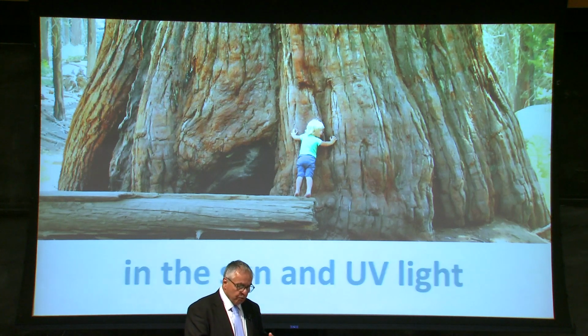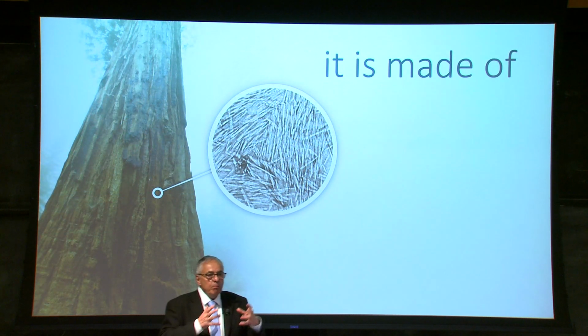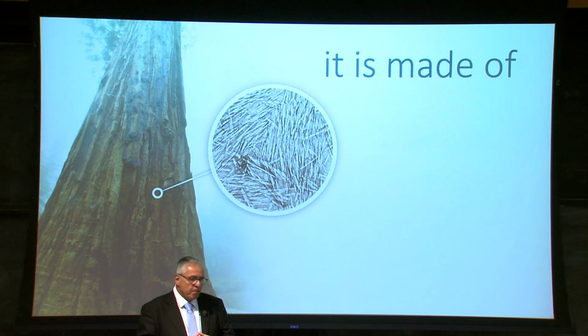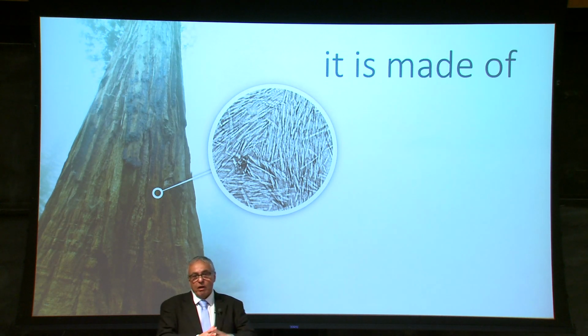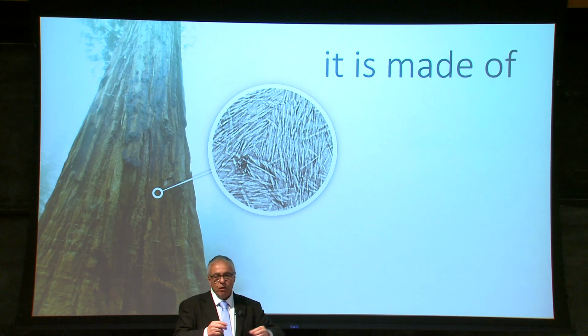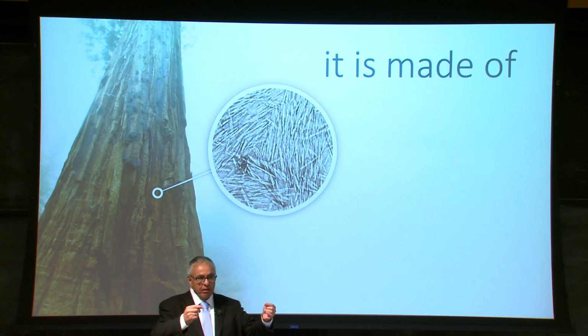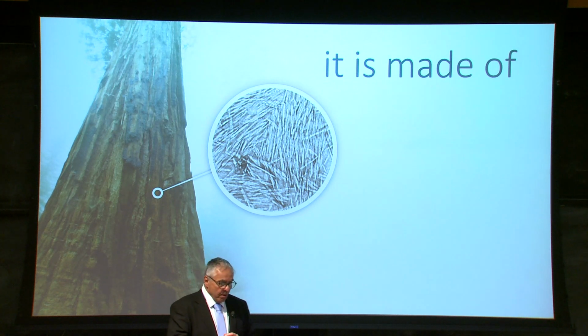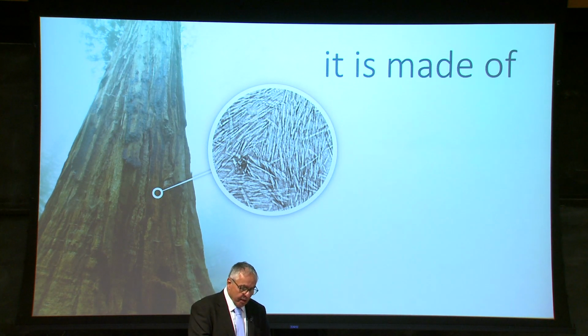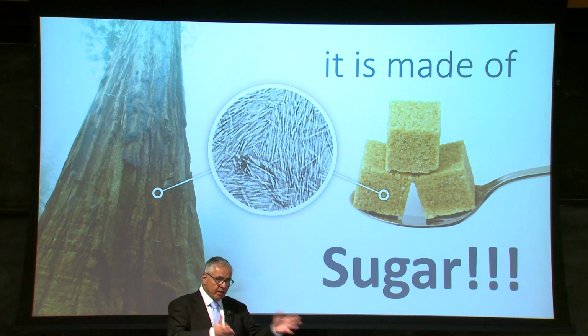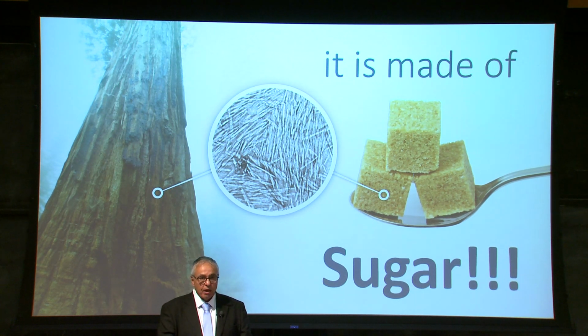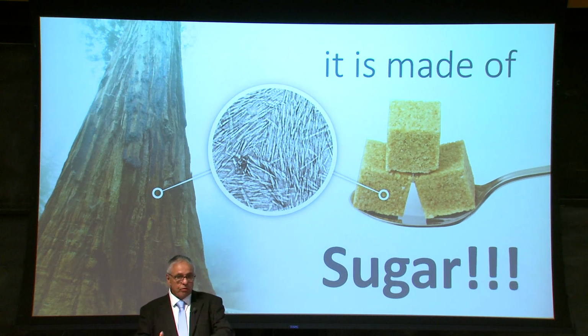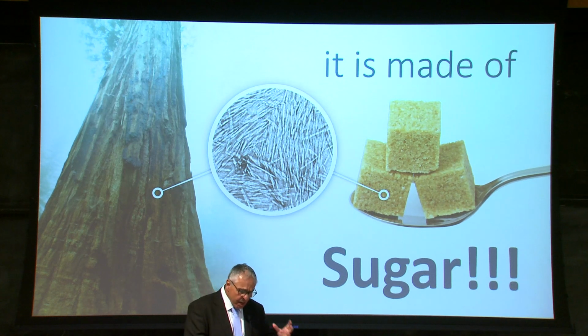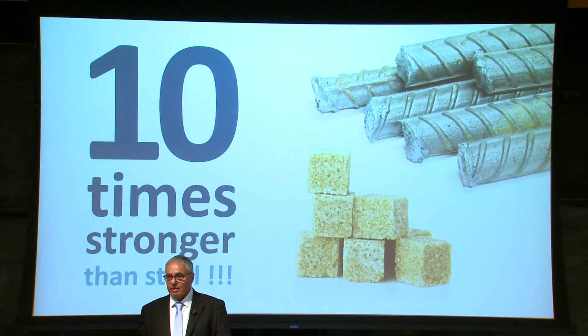Yet if you look at the structure of this tree and ask yourself, what is it really made of? How come that it is so strong? So if you look by high-resolution electron microscope, you find that at the end of the day, it is made of nanofibers, about 100 nanometer in length and about 5 nanometer in width, which are very strong, but surprisingly, they're made of sugar. Well, not exactly the same sugar we drink in our tea. It's actually a homopolymer glucose called cellulose, but it's not regular cellulose. It's highly crystalline cellulose. And this highly crystalline cellulose, on a weight basis, is about 10 times stronger than steel.